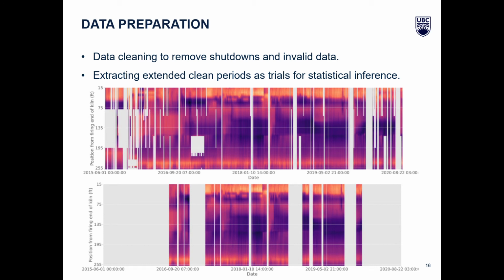The top heat map shown here is the same as the one on the previous slide, except now the data has been cleaned by removing the shutdowns and other invalid data. The bottom heat map is obtained when we sample the top heat map for extended periods of clean data from all 24 measurements. The extended periods of clean data are then used as experimental trials for developing time series models to forecast the kiln shell temperatures. Note that the largest experimental trial exhibits significant shell temperature variability at approximately 60 feet from the firing end of the kiln.